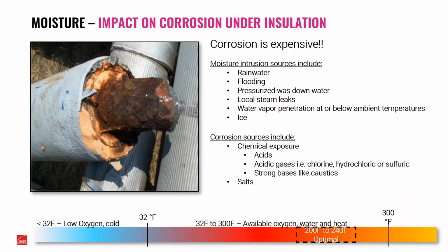And again, looking at that temperature bar along the bottom, you can see that in that 200 to 240 degrees is kind of that sweet spot. However, the 240 degree part is optimal. That's where you're going to find, again, it's hot enough that you have this hot, wet condition. You're trying to dry that water off, but it's still going to be hot and wet. And it's really going to facilitate that chemical reaction, create a lot of corrosion problems.